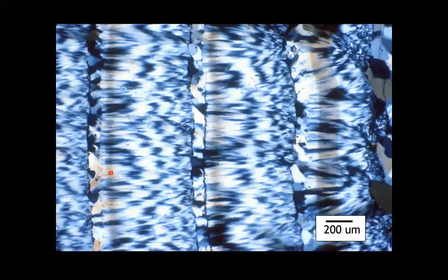And that image that you just saw taken with the transmission electron microscope corresponds to this red box that's right here. We see that now embedded within a light optical microscope picture. And I'll just tell you that this region right here is fine-grained chalcedony, and you'll notice that's alternating with coarse-grained quartz. And this fine-grained chalcedony is intensively Brazil twinned. We don't have Brazil twinning in the coarse-grained quartz. And it repeats again: fine-grained Brazil twinned chalcedony alternating with coarse-grained quartz without Brazil twins. And again, we see this repeat, chalcedony that is intensively Brazil twinned, transforming to coarse-grained quartz.